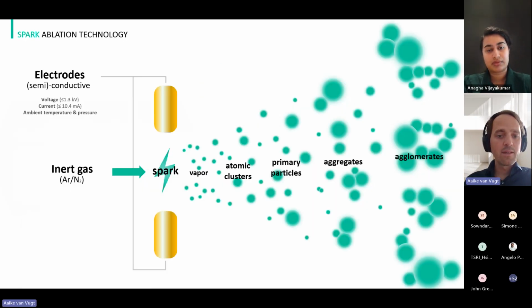So in the G1, in the source, we use those solid rods, and in between we form a spark. With the spark, we go up in temperature to 20,000 degrees Celsius or higher by creating this plasma. So basically, we directly evaporate a small fraction of the electrodes. And out of this evaporated material, we condense very small inorganic nanoparticles floating in the gas phase.